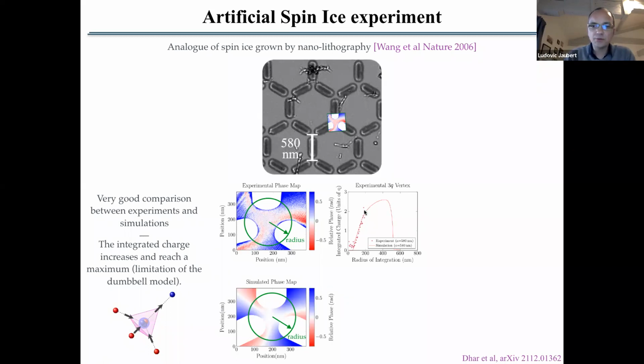But at some point, for large enough radius, which are unfortunately outside of this experimental window of measurements, we can check in simulations that this magnetic charge gets smoother, reaches a maximum, and then drops. That's because this system is a spin ice system. And so if your radius is roughly the center of the nano-islands here, you are in this dumbbell model I was talking about before for spin ice, and you can locally define these magnetic charges in the same sense as before. And so this saturation here means that you have a well-defined magnetic charge at the center of this vertex.